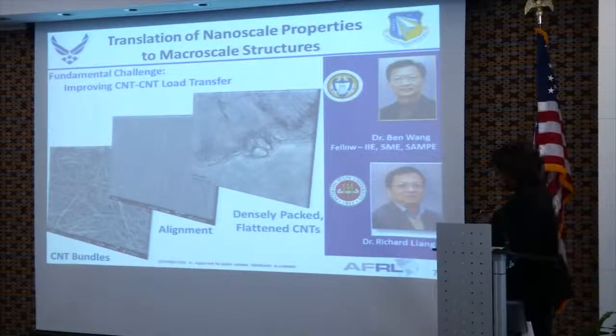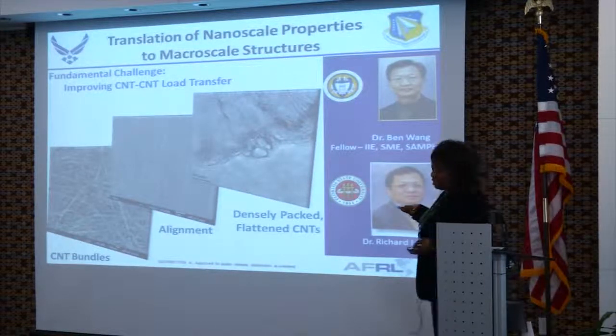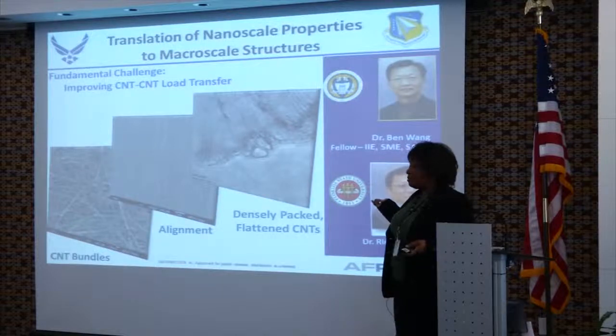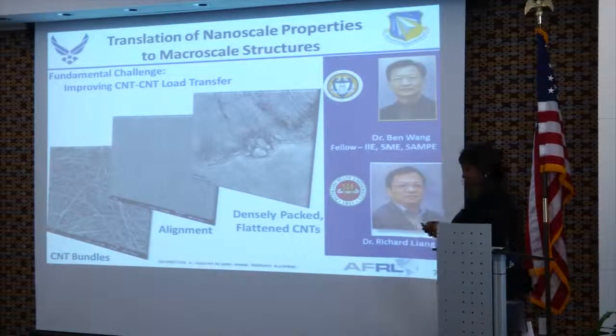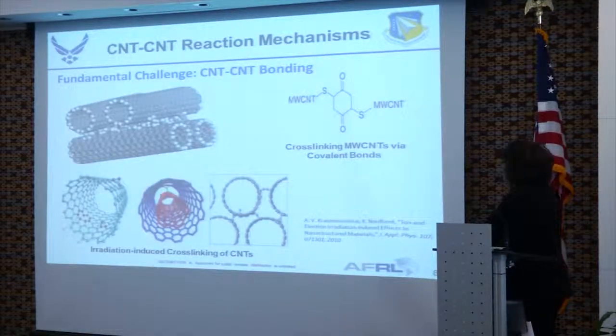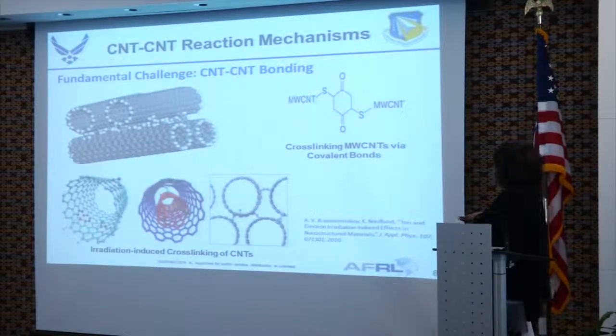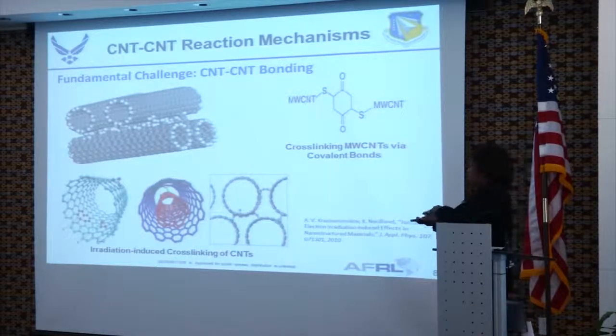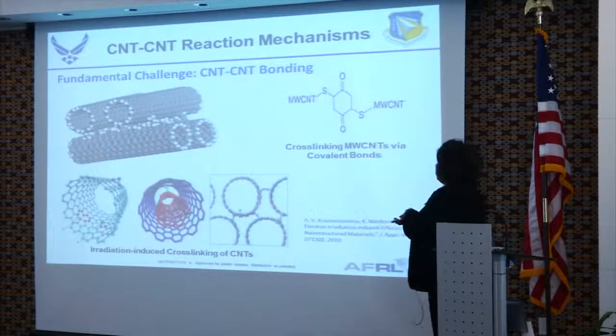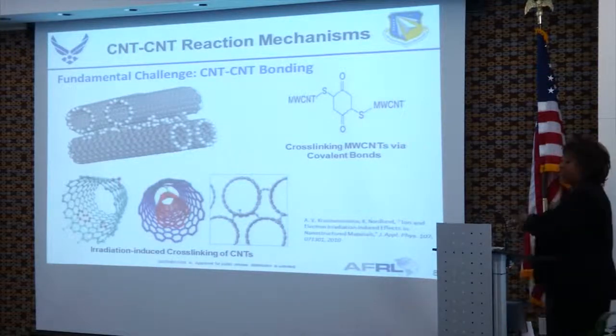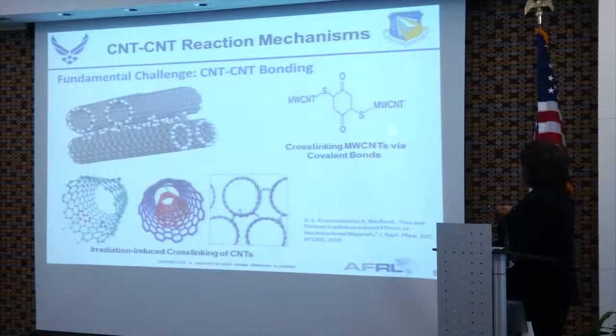The work is experimental, but it also includes theoretical modeling to try to optimize how you do this mechanical consolidation. And then the work also will advance. They're not really in this phase of the work yet. It will advance to look at how you do the chemical consolidation. You get these nice consolidated mats or assemblages, if you will, of nanotubes. How can you actually cure those, either coupling to matrix resin or coupling tubes with other tubes?